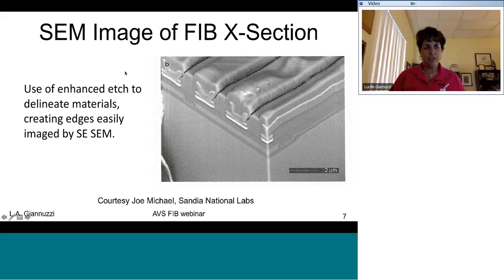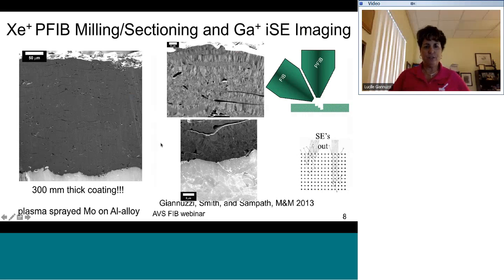The other thing that you can do, particularly in the semiconductor industry, is to use enhanced etching, sometimes called delineation etch. And what this does is preferentially mills different materials. What this also does is create edges, so that if you take a secondary electron image, SEM image, you can actually see the different edges. In addition to the material contrast here, it brings out these edges quite nicely so that you can collect SEM images after you do this FIB milling. Okay. I showed this to you earlier.